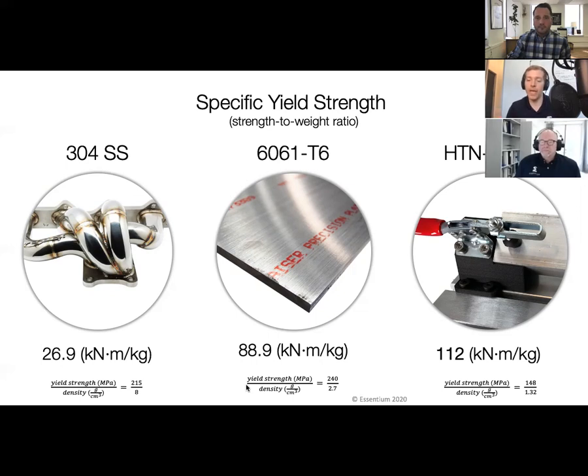And our material, the HTN CF25, actually has better strength to weight ratio than 304 stainless steel by a long shot. And then even 6061 T6, not T0, the annealed state. This is the fully hardened 6061 T6 state. We beat that strength to weight ratio. And that's pretty cool, being able to have a material that is outside of the capabilities of metals that we currently use for fixturing applications when it comes to those metrics.